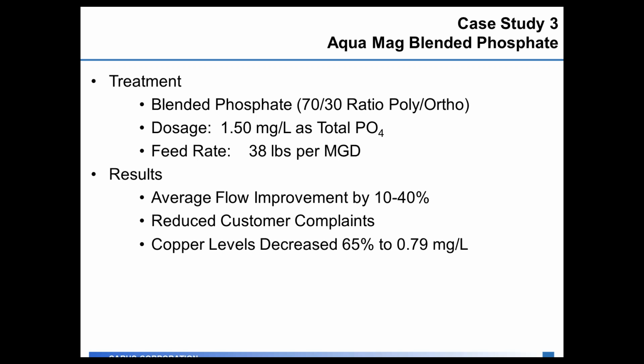They had reduced red water complaints in the distribution system as they were preventing those corrosion products from forming in the distribution system, and their copper levels decreased 65% all the way down to 0.79 milligrams per liter, so they were below the 1.3 milligrams per liter action level.